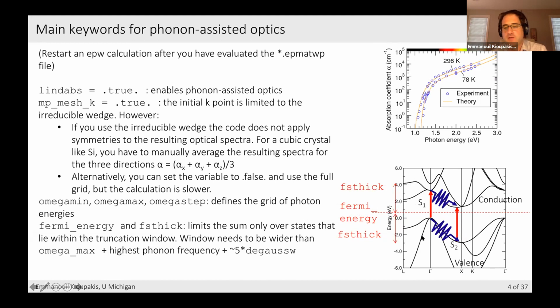So, for example, in the case of silicon and photon energies up to 3 eV, if your initial state is down at, say, -4 eV, and you absorb 3 eV, you still have the valence band. Those electrons at -4 eV will not absorb any light, so they don't need to be in the picture. You can safely start from a relatively higher energy.